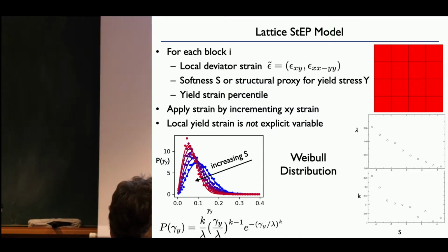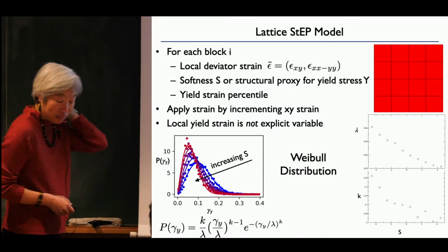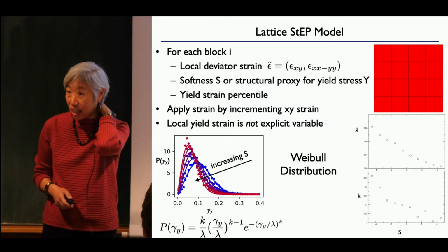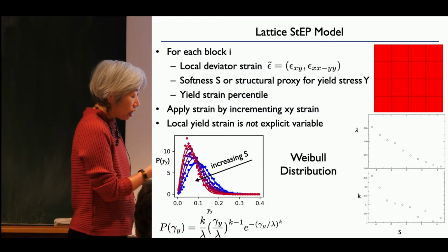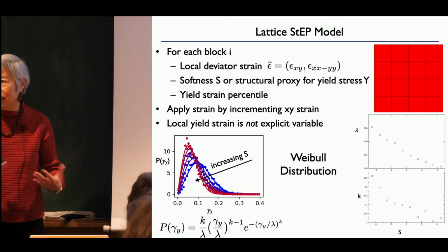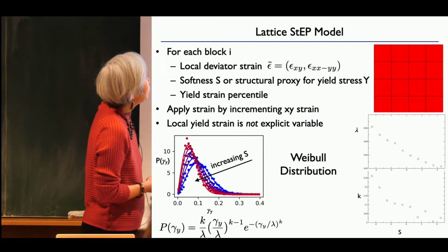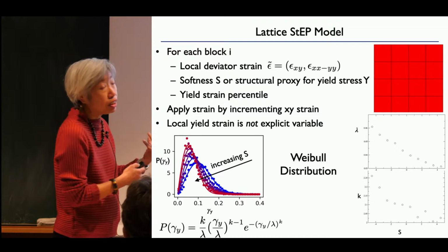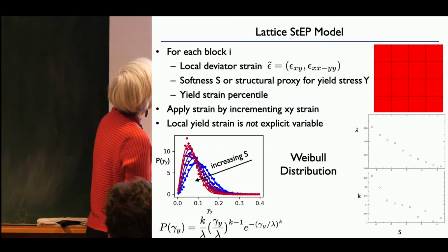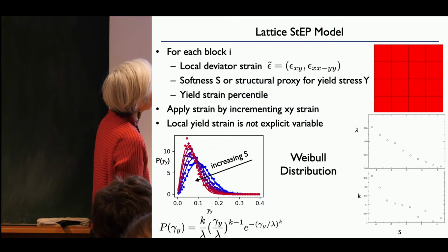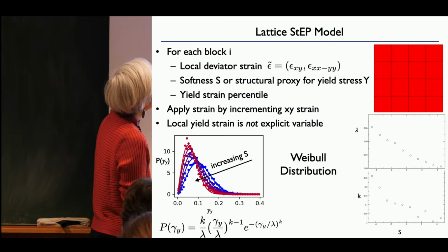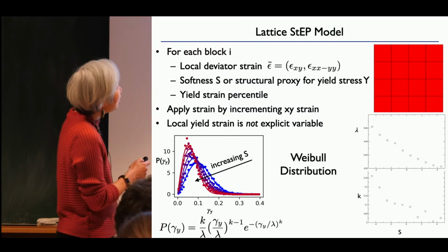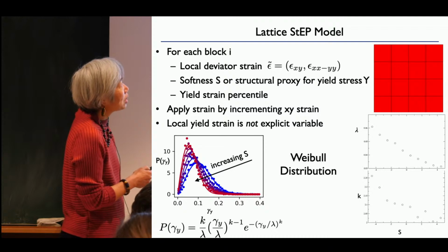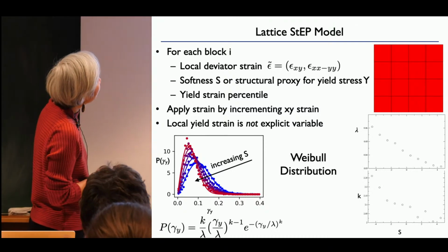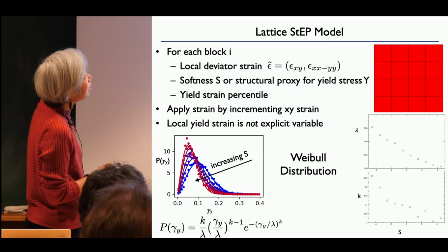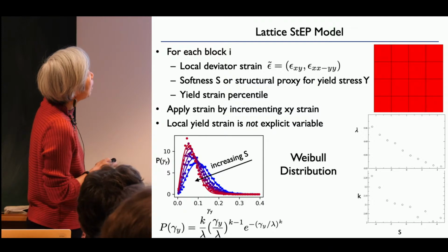Okay, so what we do is we develop a lattice model that's similar to the elastoplastic model, except that it contains structure. So we call it the structural elastoplastic model, which is a mouthful, so we call it the STEP model for short. And this includes that interplay that I was just describing. In this case, we put two components of strain. The local deviatoric strain is a tensor. It's got components epsilon xy, xx minus yy. So we keep each component. We keep the softness on each block.